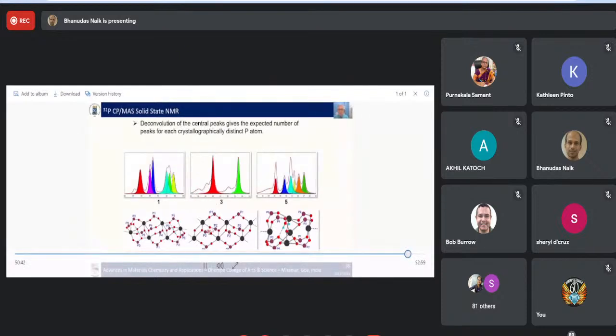it is. Compound 3, which only has 2 distinct phosphorus atoms, only has 2 principal peaks here, and you have a small amount of the hydration here, and you also have this extra peak on this side. And compound 5, which has even more peaks, we have 8 distinct phosphorus atoms in compound 5. As well, you get 1, 2, 3, 4, 5 peaks, but you can see that 3 of them are much bigger than the other 3. So you have 1, 2, 3, 4, 5, 6, 7, 8.